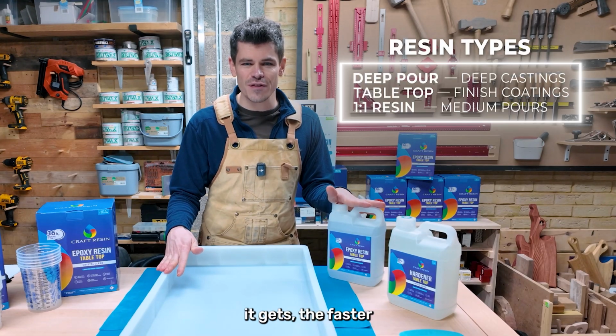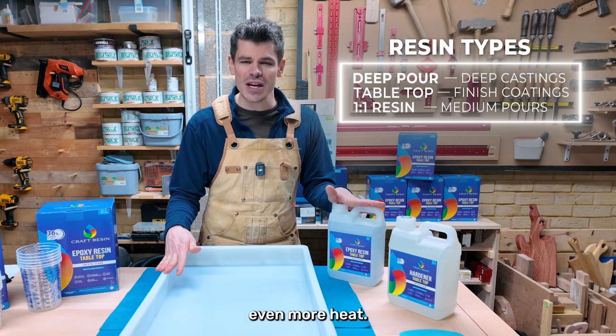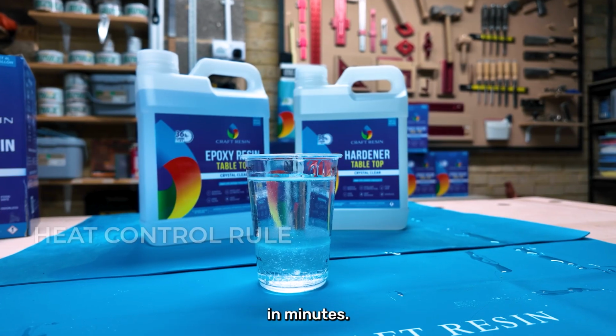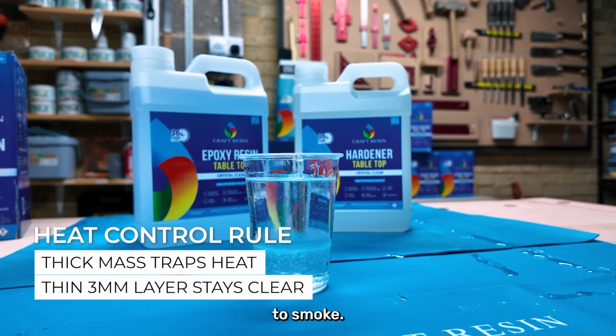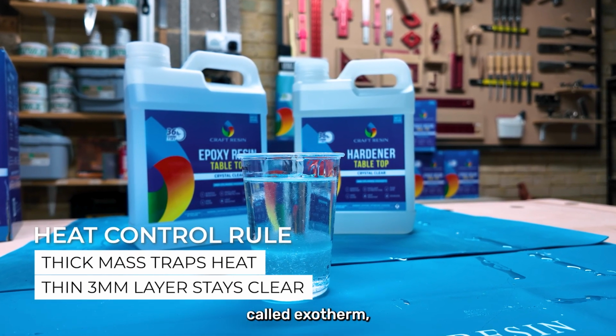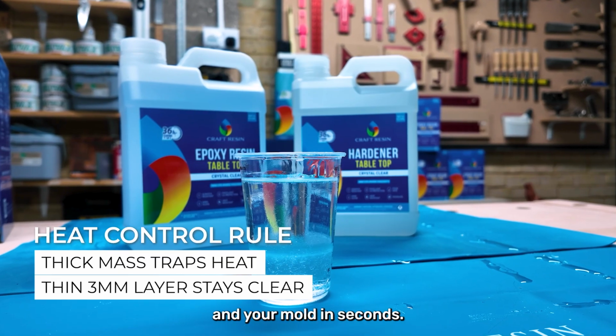This creates a snowball effect. The hotter it gets, the faster it cures. This makes even more heat. Soon the resin thickens in minutes. It turns yellow and can even start to smoke. This rapid reaction called exotherm can ruin your project and your mould in seconds.